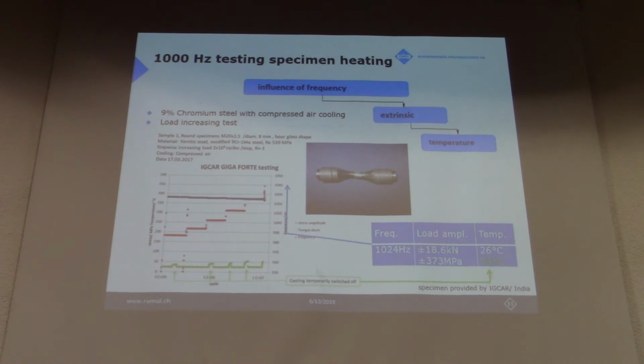With every cycle, and especially if there is some small portion of plastic deformation somewhere in the material, this damping is then dissipated to heat, and we see that in a temperature increase. The higher the frequency, the more heat is produced per time, of course.